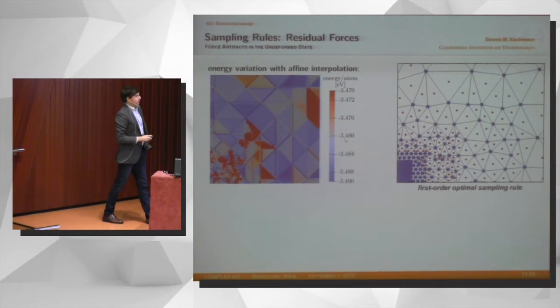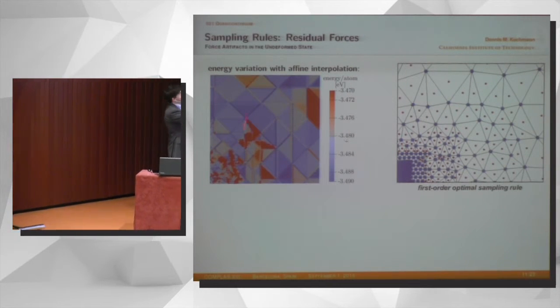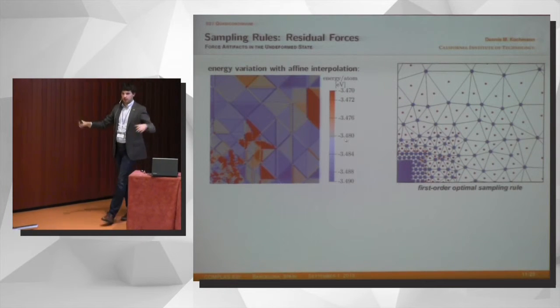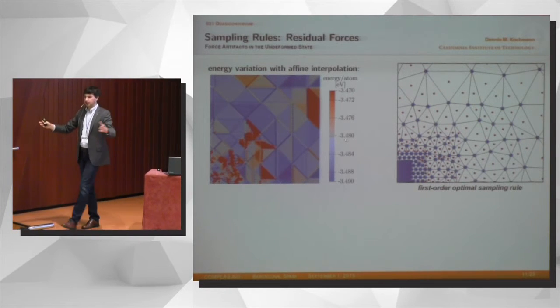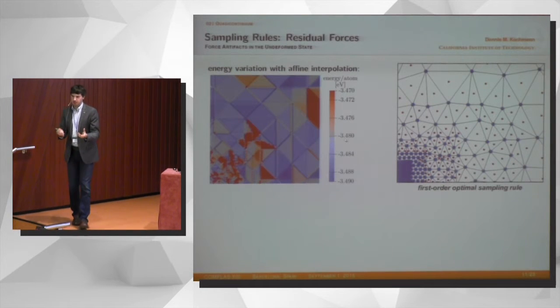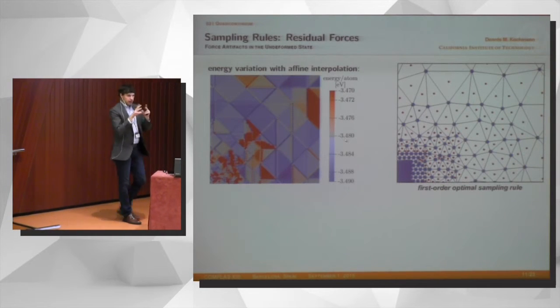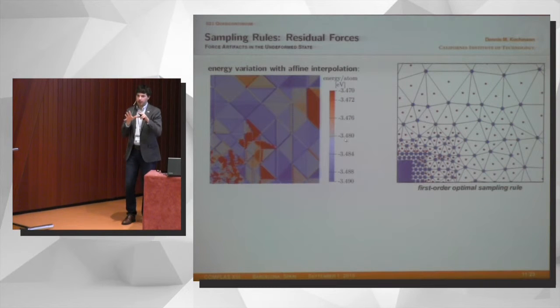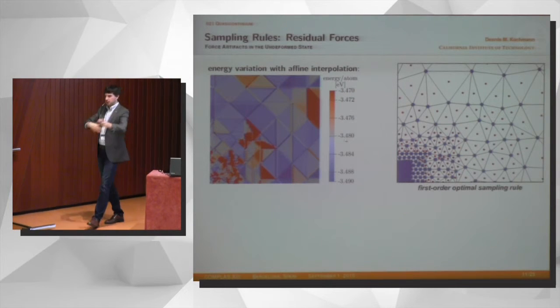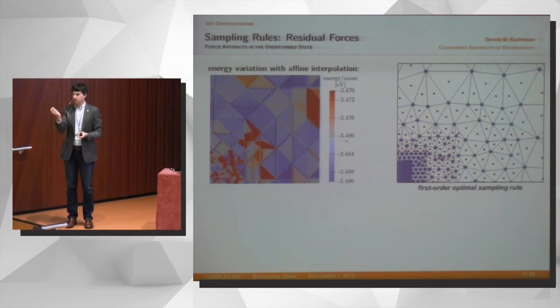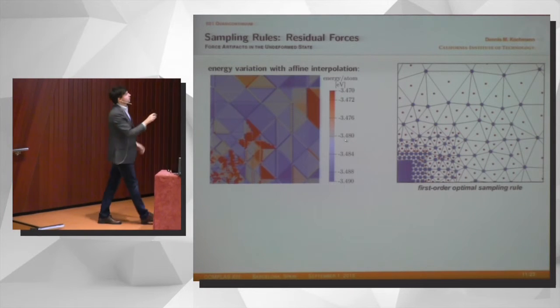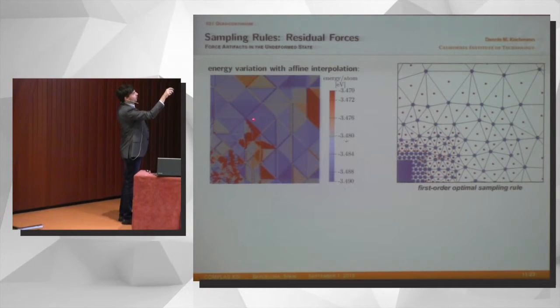And this sampling scheme actually makes perfect sense, because let's assume we use a linear interpolation. If I use a linear interpolation, that means my deformation gradient is constant within each of the elements, right? And if this is the case, that means all the atoms on the inside of an element are deforming in an affine manner. If all the atoms are deforming the same, that means each atom sees exactly the same neighbors. And as a consequence, the energy inside each element is constant.